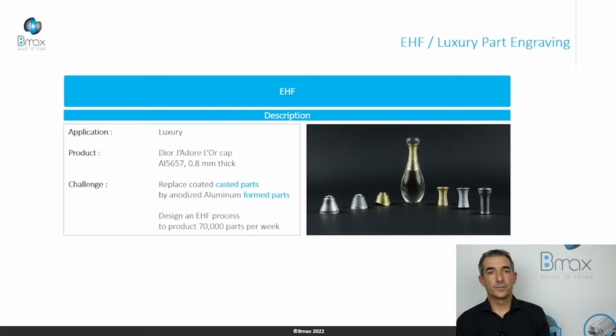This first example consists of engraving the J'adore L'Or cap. The material is 5657 aluminum, annealed, 0.8 millimeter thick. The objective is to replace the coated cast part by anodized aluminum, and we designed the EHF process to produce with a high production rate, 70,000 parts per week and 1 million parts per year.